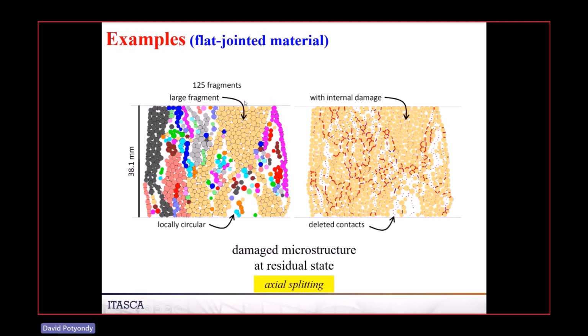This is the fragments that it has broken into. And then this is the same system, but now we're just looking at the broken bonds, the broken elements. And again, thickness is proportional to the magnitude of how far they're open. So you can see there's all kinds of partial damage in here, but the main deformation is happening where these guys are bigger.